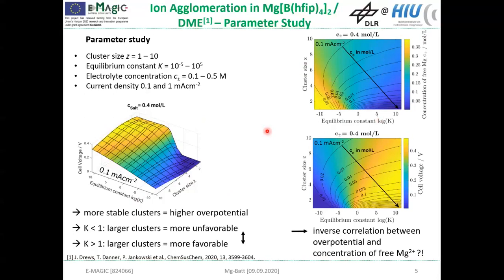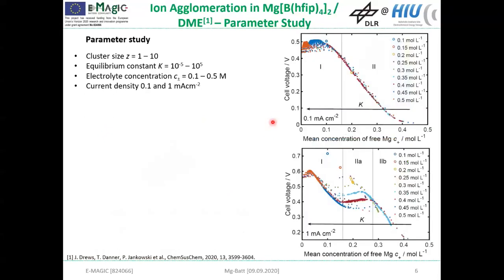And that's the reason why we have a closer look at the relation between the cell voltage and the amount of free magnesium. So these two graphs show the results for the two different current densities, and each data point in this graph represents one K and Z combination at a certain electrolyte concentration. By including and excluding the different effects of the cluster in our model, it was possible to explain the different features of this graph.